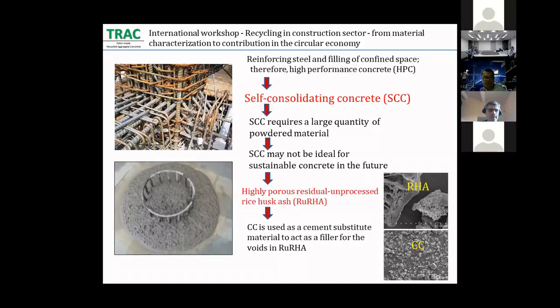In particular, bleeding of concrete paste, especially Portland cement and water, is the main parameter that determines the short- and long-term properties of concrete, such as strength development and durability. However, self-compacting concrete requires a large quantity of powder materials, especially Portland cement, compared to normal concrete to generate high-flow concrete. With the greater amounts of Portland cement required, self-compacting concrete may not be ideal for sustainable concrete in the future. Therefore, new alternative cementitious materials have been considered. A promising approach is the utilization of agricultural and industrial byproducts to replace Portland cement.